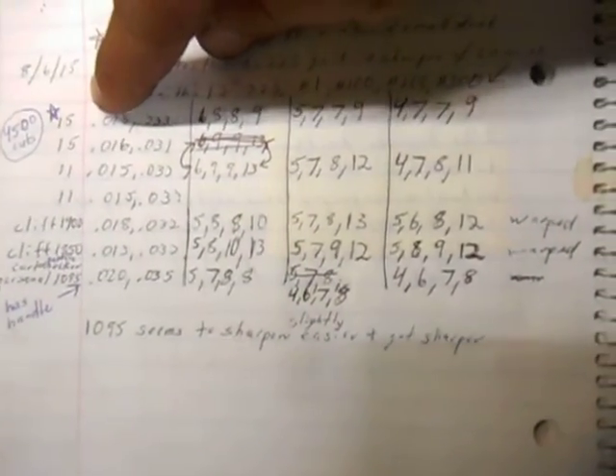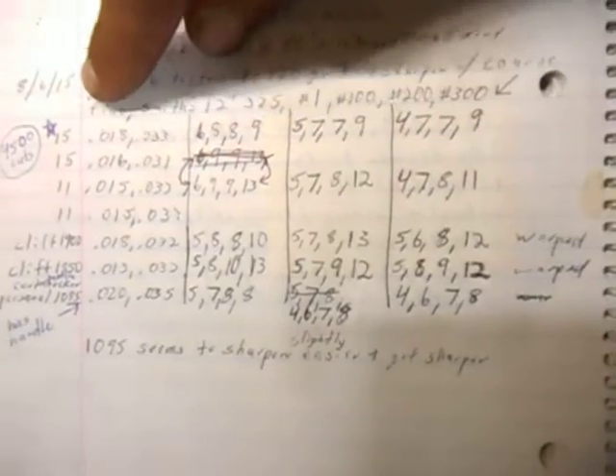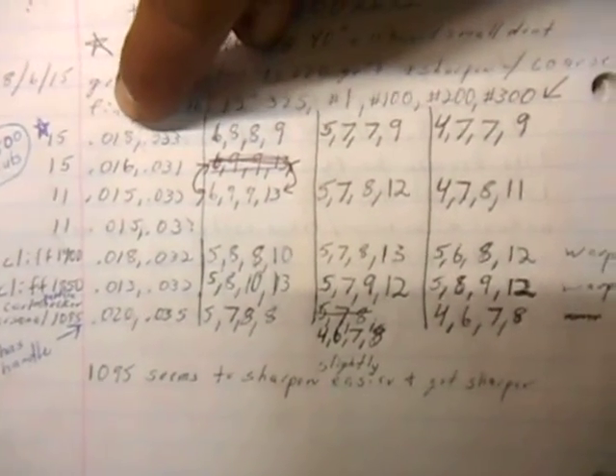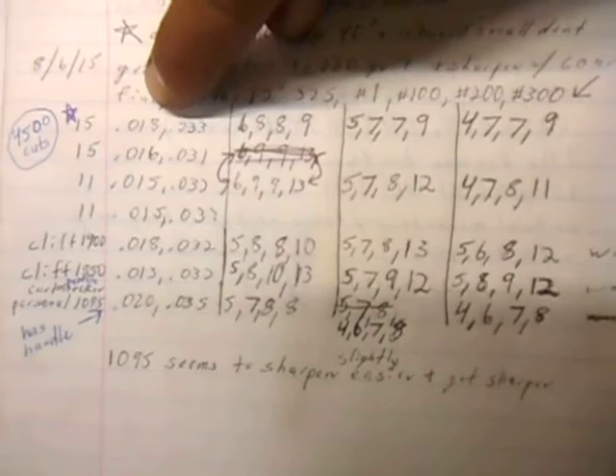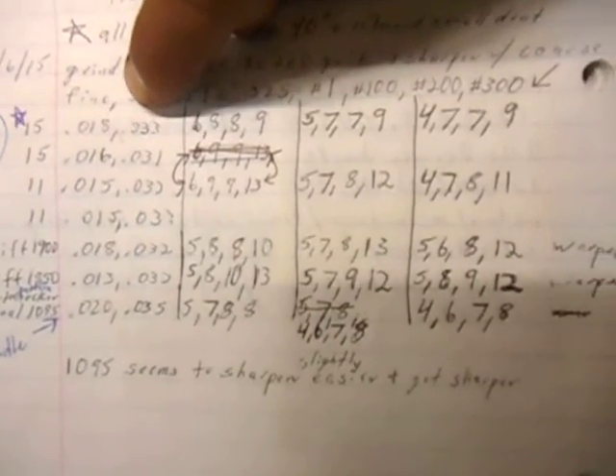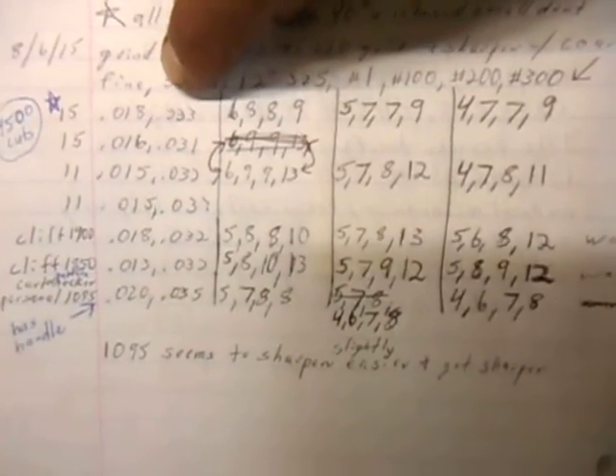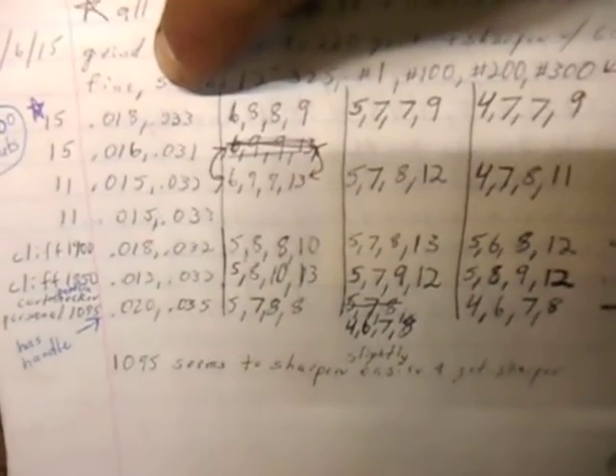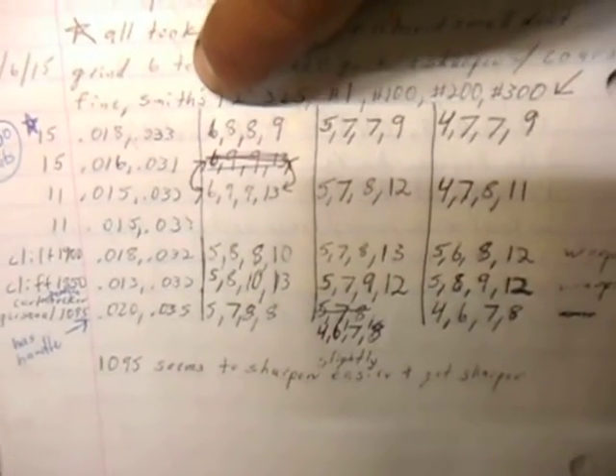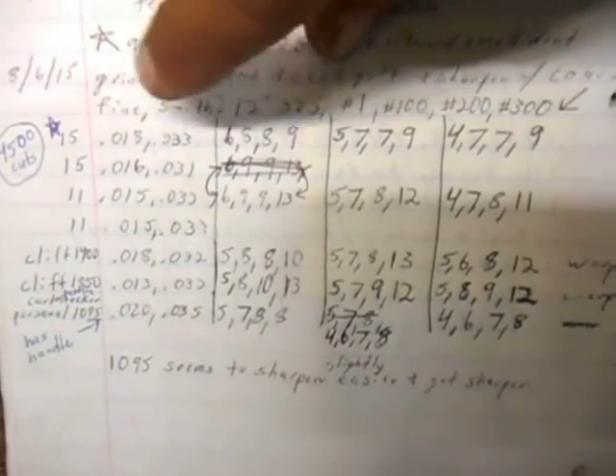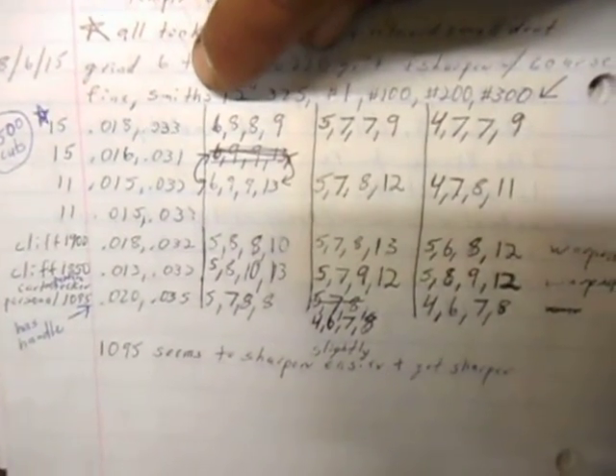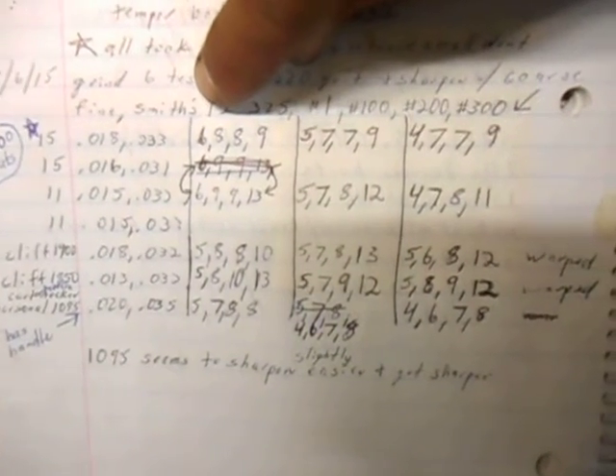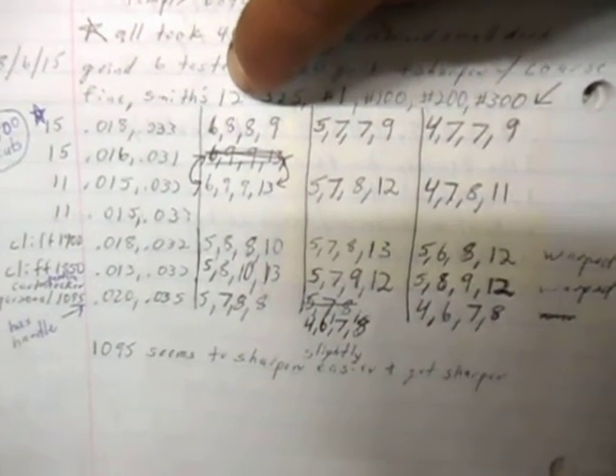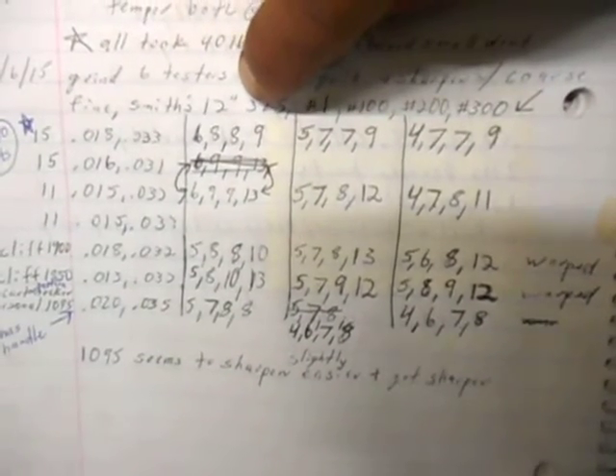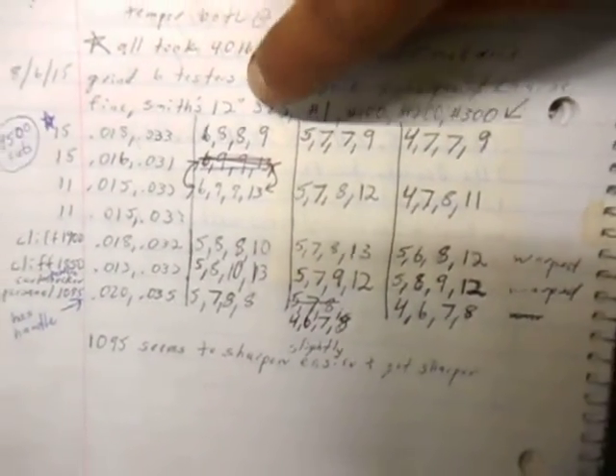The best one was the 15-minute single quench. It measured 18 thousandths behind the shoulder of the edge, and measured 33 thousandths a quarter inch back from the edge. You can see that a little bit better. The first cut on the first test took 6 pounds to complete. 8 pounds for the 100th cut, 8 pounds for the 200th cut, and then 9 pounds for the 300th cut. And that's what those numbers mean on all of these.